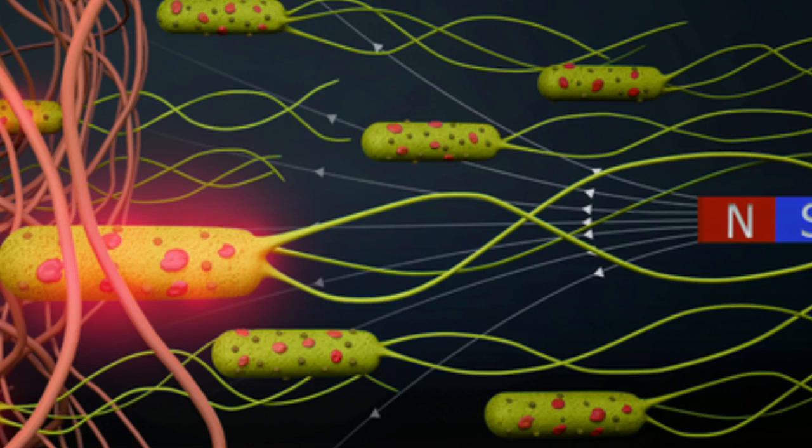Once the microrobots are accumulated at the desired point, the tumor spheroid, a near-infrared laser generates rays with temperatures of up to 55 degrees Celsius, triggering a melting process of the liposome and a release of the enclosed drugs. A low pH level or acidic environment also causes the nanoliposomes to break open, hence the drugs are released near a tumor automatically.